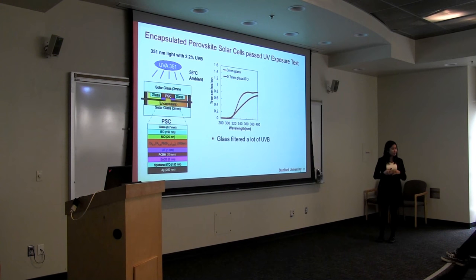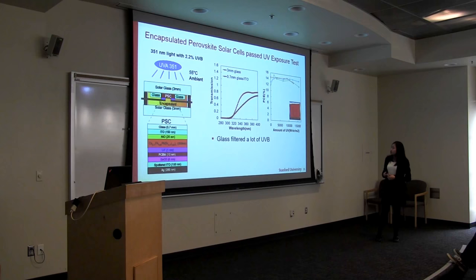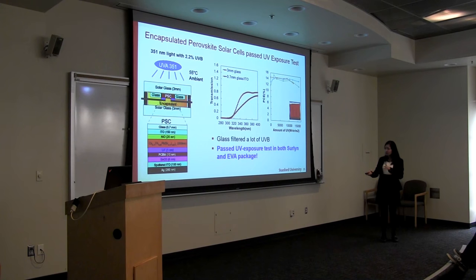I was curious how much UV actually gets onto my cell. So I measured the transmission of the light through the two glass layers, the thick solar glass and the perovskite substrate. I saw that the glass did quite a good job filtering out the UVB, but we still have a lot of UVA in this area, which could degrade perovskite. But when I put this package under another IEC standard, which requires 15 kilowatt-hours per meter squared, we see that all 3 solar cells passed this test, and we didn't see any change in the color. So, agreeing with Thomas and the community, removing titanium and using something that's more robust to UV can make perovskite stable under UV exposure.